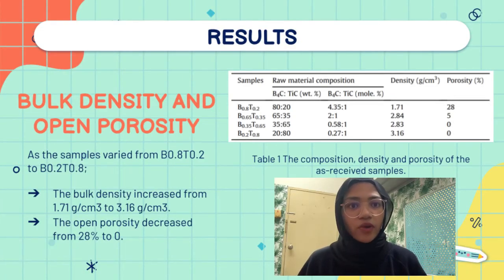Density increased from 1.71 gram per cm cube to 3.16 gram per cm cube, and the open porosity decreased from 28% to 0 as the samples varied from B0.8T0.2 to B0.2T0.8. During the aluminium-silicon melt infiltration process, boron carbide reacted with aluminium to form a ternary aluminium-boron-carbon phase that acts as a barrier to aluminium-silicon melt infiltration and results in high porosity in infiltrated samples with a higher boron carbide fraction.